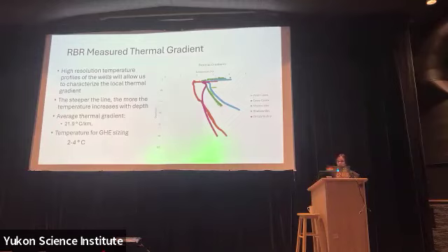future. So another really important metric for ground source heat pump systems is the temperature of the ground. And what we do is we use an RBR probe to measure the thermal gradient over the course of the well. So we essentially are lowering a temperature data logger slowly into the well to see how the temperature is changing with depth. And you can see at the top of these wells, we have a temperature that's being influenced by the air temperature. And then as you're going down into the well, this temperature is not being influenced by the surface temperature as much anymore.